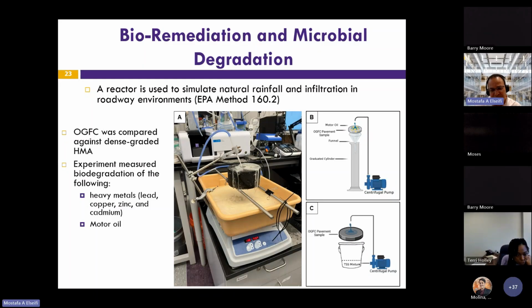To look at the biodegradation, what we did is we had a dense graded and an OGFC specimen. We subjected them to two types of contaminants. We subjected them to heavy metals, which included lead, copper, zinc, and cadmium, and we subjected them to motor oil. We used EPA method 160.2 to assess how much biodegradation you will get in the specimen when you pass these contaminants through the specimen. So you have this filtration process and you have the biodegradation. The good thing about OGFC is that you have this high storage capacity of contaminants, and that allows the biodegradation of these pollutants. And I'm going to show you the results.